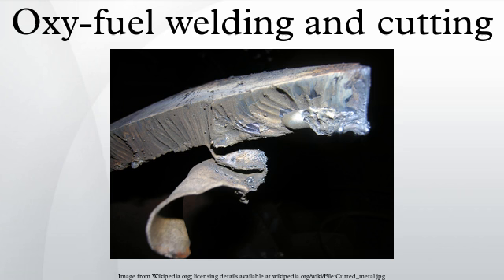Oxyacetylene can cut only low to medium carbon steels and wrought iron. High carbon steels are difficult to cut because the melting point of the slag is closer to the melting point of the parent metal, so that the slag from the cutting action does not eject as sparks but rather mixes with the clean melt near the cut. This keeps the oxygen from reaching the clean metal and burning it. In the case of cast iron, graphite between the grains and the shape of the grains themselves interfere with the cutting action of the torch. Stainless steels cannot be cut either because the material does not burn readily.